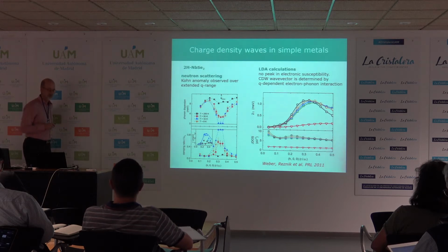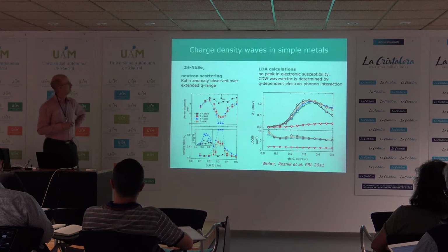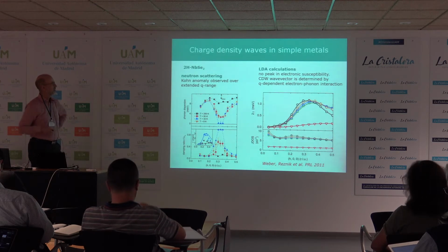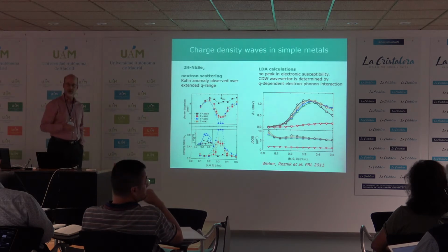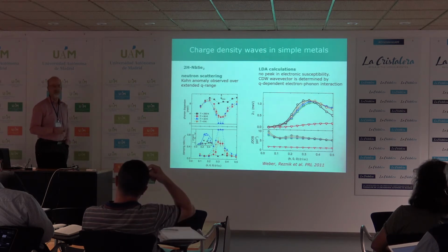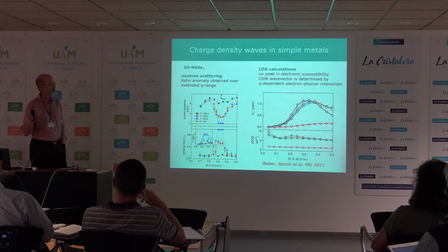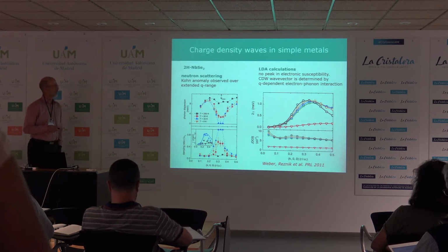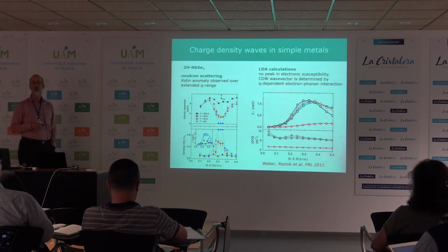the standard picture of nesting, which I just showed you in the Peierls work, is not what's really causing the charge density wave of these materials. Rather, the wave vector of the charge density wave is determined not so much by the electronic nesting or electronic susceptibility anomaly, but by the electron-phonon interaction. That's a message I'd like you to remember also for our discussion of charge density waves in cuprates. Okay. Is there a material where it is actually looking like classic nesting?